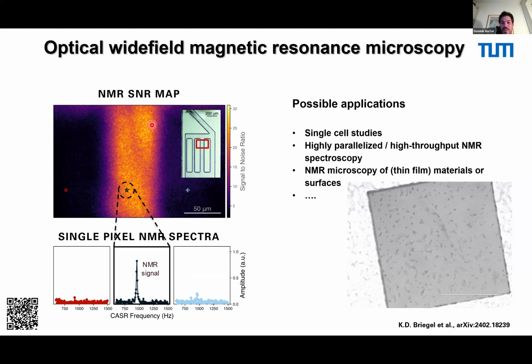And what was the issue? They removed everything magnetic from this objective, but the coating was made of nickel. This nickel coating was still so magnetic that it killed our NMR signal. Then we were very lucky that we had another objective around, randomly, which reduced it much more. But you see here the line width is still 10 to 15 hertz. If we remove the optics and go back to our standard non-imaging experiment, we should be at 2 hertz. So at the moment we are limited by our engineering capabilities, unfortunately. Well, fortunately, but it's hard work to get rid of the line width. It's not limited by the NV properties.